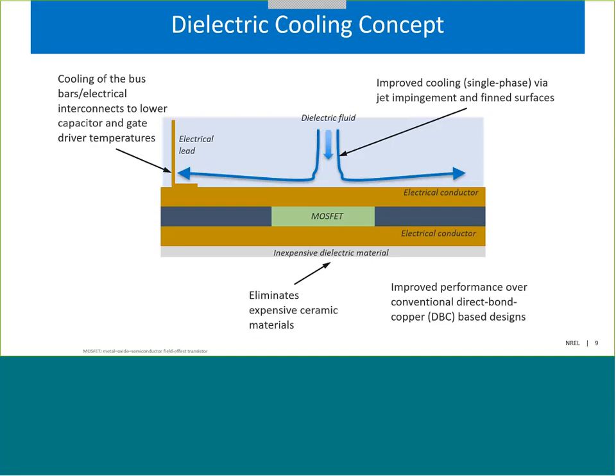Another benefit of this cooling approach is that you can eliminate the expensive ceramics that are typical for DBC-based packages. If you look at the schematic here, the dielectric material that's shown on the bottom is not in the heat flow path because the heat flows upwards towards the fluid. Because of that, the dielectric material does not need to be thermally conductive. It can be made out of something that is inexpensive. So there's that added benefit of using a dielectric fluid.